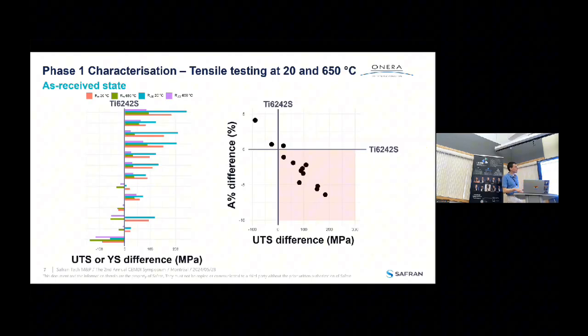I'm going to go through just 2 slides of results, and I think the most interesting one actually is this graph. So it's the results of tensile testing at room temperature. It's far from being the only thing that we did. And what is plotted is the ductility difference to Ti6242 as a function of the ultimate tensile stress difference. And so ideally, we would like to be here, to have material with better ductility and resistance. But you can see that the 13 alloys actually didn't beat the physics behind resistance and ductility. If you gain resistance, you lose ductility and vice versa. This is basically what is represented there, but you can see that generally we found some alloys with better